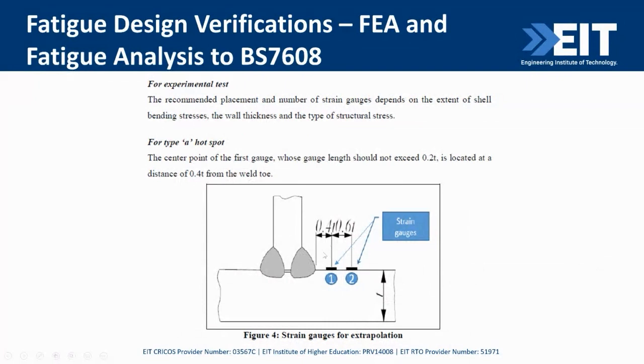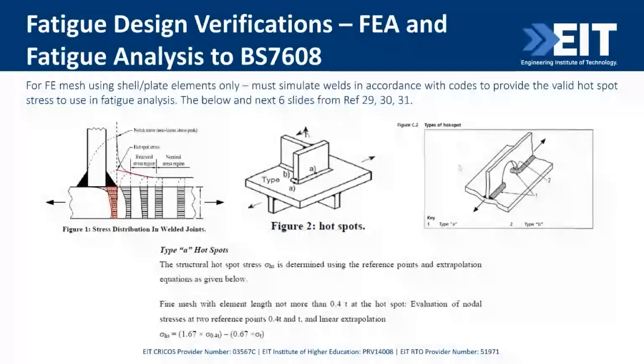So if you're strain gauging, you'll use a gauge at 0.4T and 1T or 0.6T away from here. And that gauge can't be more than 0.2T long, otherwise it'll average too much over that area. This is from a paper, an excellent paper, two papers, references 29 and 30. I suggest you get those, easily downloaded.